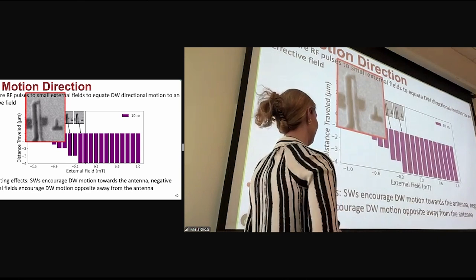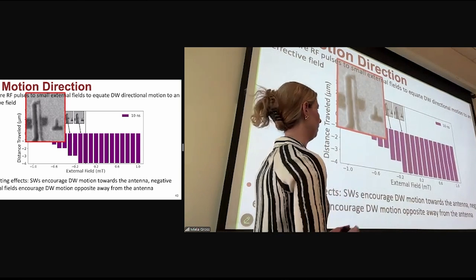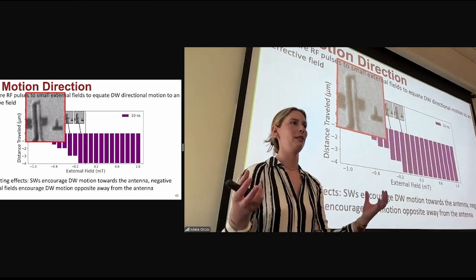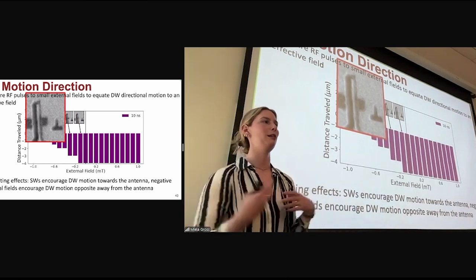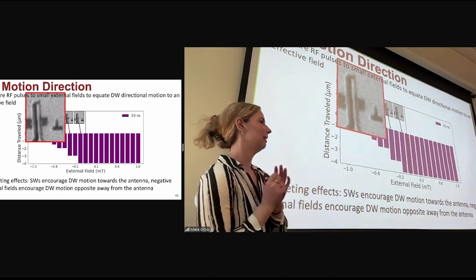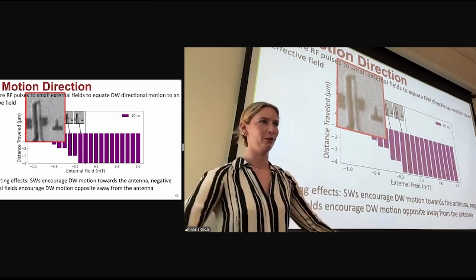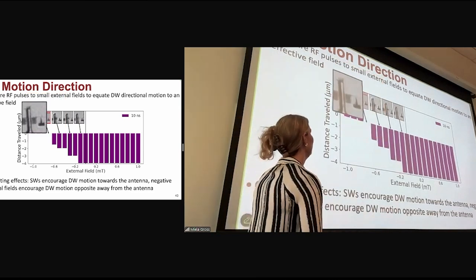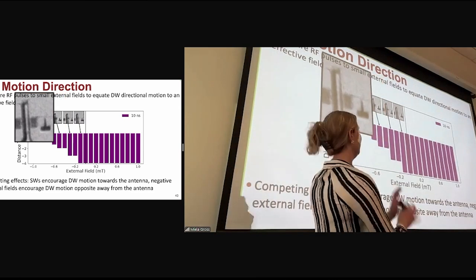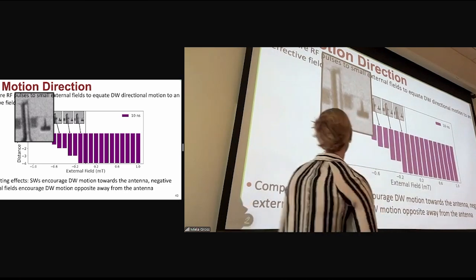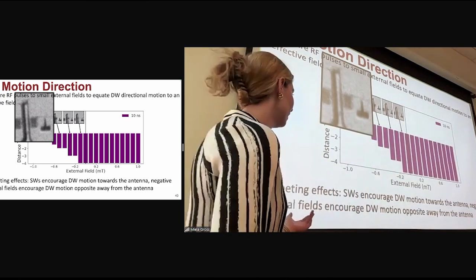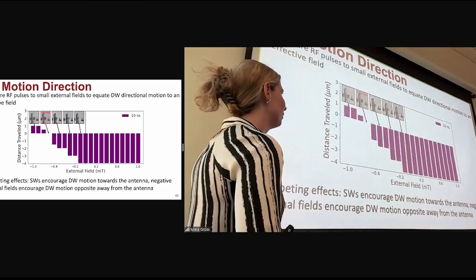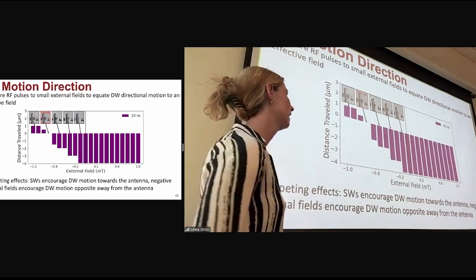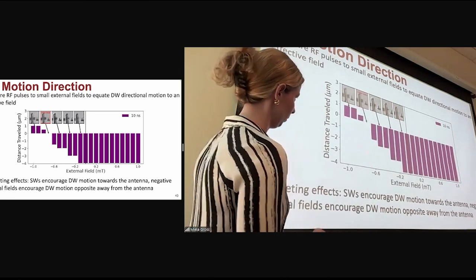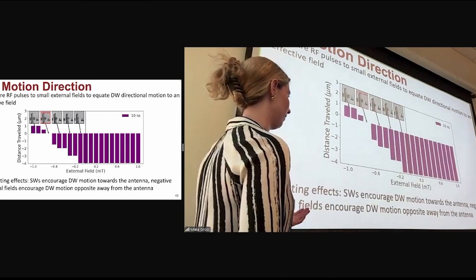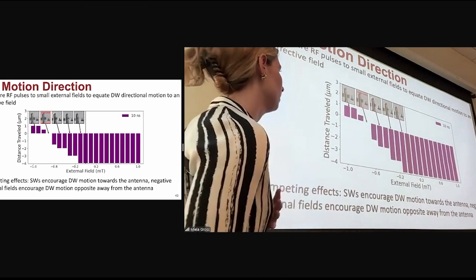And that we're going to call an effective field of our spin waves, because we have equal and opposite competing effects of the spin waves trying to move the domain wall to the left and the negative fields trying to push the domain wall to the right. And if we keep increasing that negative field, we see the domain wall actually start to move towards the right because it's dominating this regime here. So I did that for a couple different pulse conditions, and this is the resultant plot of what we found for just 10 nanosecond pulses.